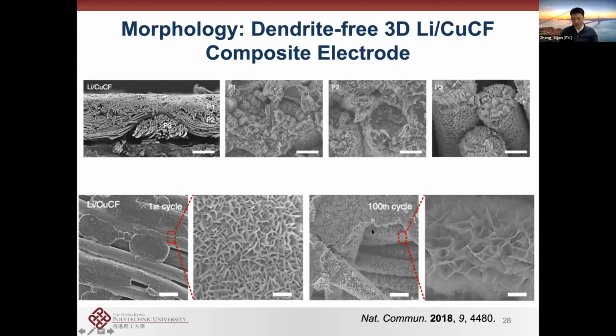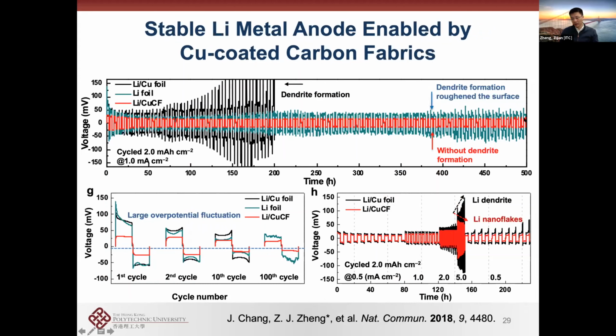It comes up with a very thin, uniform film coating on top of the electrode, which is great because the key issue of lithium metal is the formation of dendrites, the aggregation of microstructure. In this case, we don't see any dendrite formation. Therefore, the device should be very, very stable. You run a long-term stability test, and you see that the overpotential has been kept very, very small and very stable, even at this kind of high current density, at 5 milliamperes per square centimeter, which is considered really high. The electrode was still very stable. If you compare the black curve, which is the control device, they form lithium dendrites, and the device will short very easily.